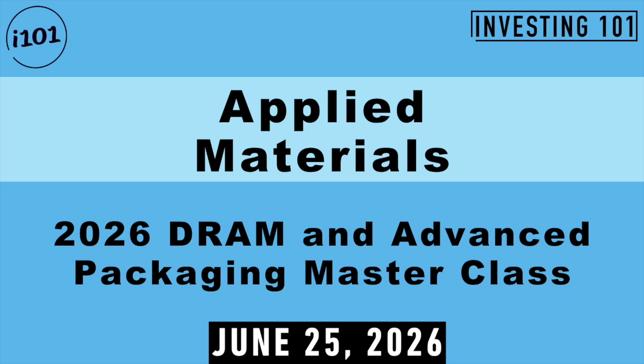Applied's leadership in the most critical of these TSV formation and interconnect steps has given us the #1 market position in HBM packaging. Applied today introduced a new product that helps our customers work with thinner HBM DRAMs to squeeze more of them into a given stack height. HBM dies are thinned to around 1/25th of the height of a standard DRAM wafer, which makes them susceptible to bowing. The higher the stack, the higher the risk of alignment errors, bonding failures, and yield issues.